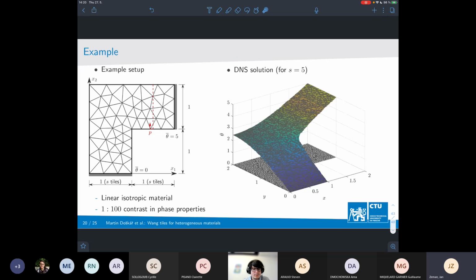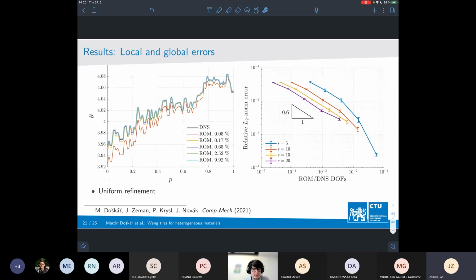So this is how the direct numerical solution looks like. So you can really see that there are fine details I would like to recover. This is what I will see from my reduced model, given here using this partition of unity type of ansatz. So if I have a look at the reference solution, this obtained by direct numerical simulation, and if you zoom through colors, you can see that actually starting from this purple one, the remaining colors cannot be distinguished. So I mean, at this fraction of the number of degrees of freedom, you get very, very accurate local fields.